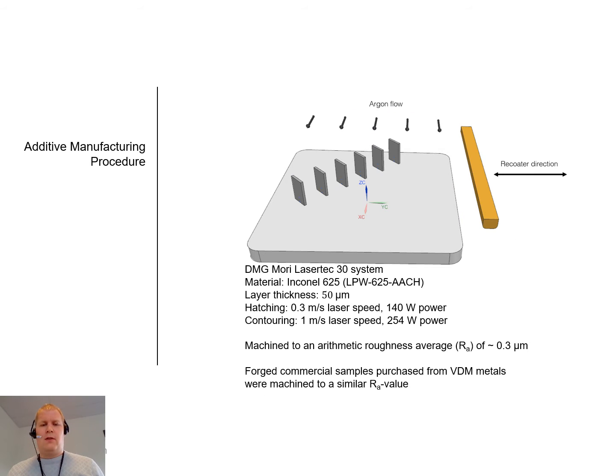For the additive manufacturing process, we used the DMG Mori LaserTec 30 system, and here you can see an illustration of how the production was done. You have the argon gas flow in here, and you have the recoater direction this way, and here you have the metal samples. The layer thickness was 50 micrometer. During the hatching, the laser speed was 0.3 meter per second and 140 watt power was used. During the contouring, 1 meter per second laser speed was used and 254 watt was the power of the laser.